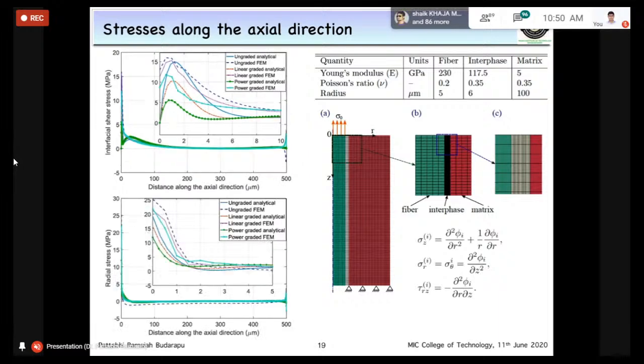So the bottom line is, by appropriately grading the material modulus of the interface, we can reduce the peak stresses. And similarly, the radial stresses are plotted here. Again, the similar trend, the peaks are dropping within a small distance, from let's say 25 megapascals to more or less less than 1 megapascal within a distance of 2 micrometers. That's the important part.